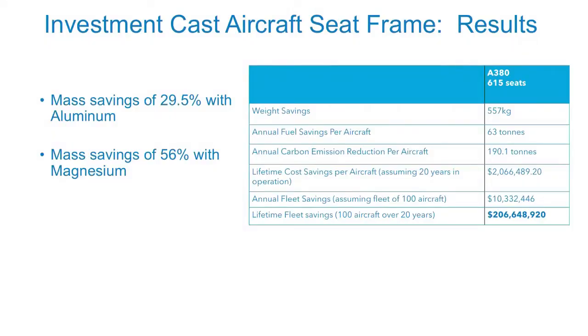So we're pretty excited about what we're able to achieve here using geometry optimization alone, using the adaptive latticing that Andy did. We were able to reduce the mass of the original seat frame by about 30%. What's really exciting here is we're able to reduce the mass by another almost 25%, just with the switch from aluminum to magnesium alone. Magnesium has a higher specific strength, a higher strength to weight ratio. So we're able to actually, in the end, reduce the weight of this part by a factor of 2, which is pretty exciting.